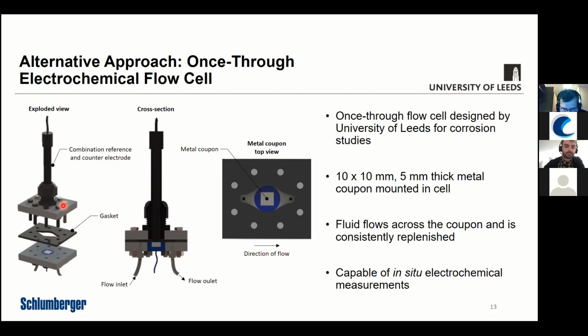So in the top layer, we've got a combination reference and counter electrode. And in the bottom layer, we've got our carbon steel sample, which we embed in an acid-resistant resin. We would grind that surface once we've set the coupon within the cell, so that we've got a perfectly smooth flow path for the fluid to flow across.